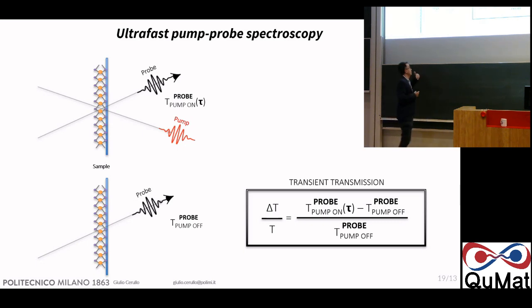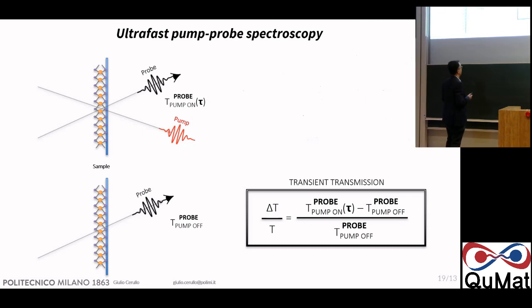And with the probe pulse, you measure how these optical properties, how the transmission or reflection changes as a function of time after the pump has arrived. The time resolution is really given by the delay between pump and probe, which can be controlled very precisely by a mechanical delay line. So by scanning a mechanical delay line, you can change the delay between pump and probe, and you can control this, you can measure your signal.